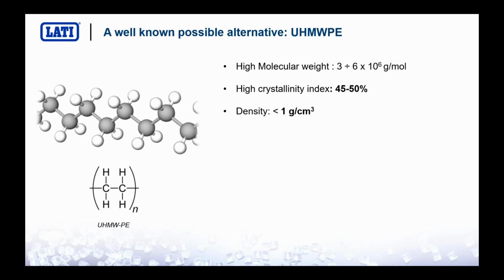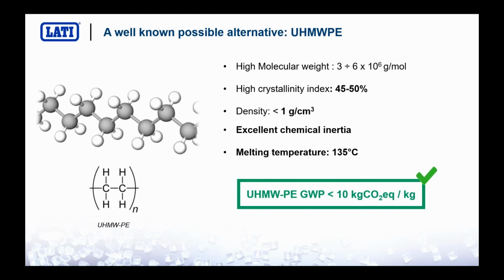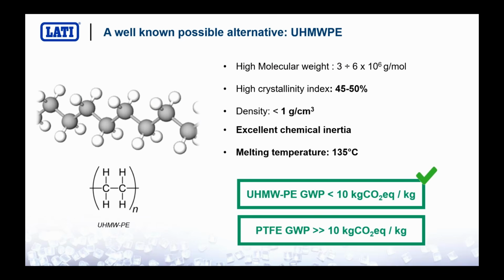The density is lower compared to the PTFE, which is higher than 2. In this case, it is lower than 1, so very low compared to the PTFE, with an excellent chemical inertia, like all the polyolefins, like polypropylene, polyethylene, and so on. A low melting temperature, around 135 degrees, so 200 degrees lower than PTFE. But another advantage is also the GWP, so the carbon dioxide emission to produce 1 kilogram equivalent of the product, which is really lower compared to the PTFE one.